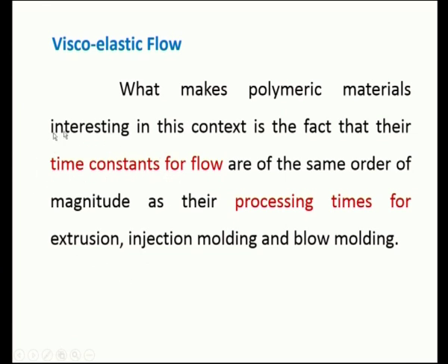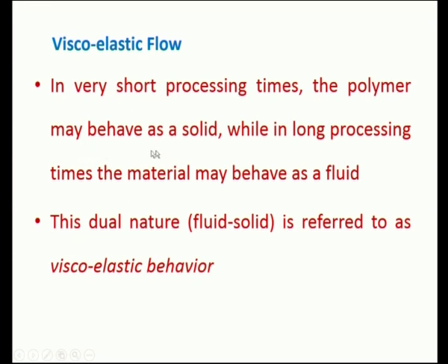In first order system you have one time constant, for second order system you have two time constants, and then this time constant and the processing time have a direct relationship, or the magnitudes are of the same order for a polymeric system. In very short processing times, the polymer may behave as a solid, while in long processing times, the material may behave as a fluid. That is, short processing time refers to short molding time. Molding time is the time the resin takes to fill the mold before it is ejected out as a final product. So therefore, in short processing time, the polymer has to behave as a solid.